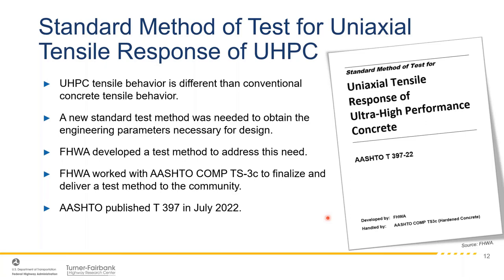AASHTO T397 was published in July 2022, so just a couple months ago. This is a test method that my group developed. We actually started working on this about a decade ago. Tested it many times. Various other labs have tested it. There's a pooled fund study that's looking at this method as well that's going to soon publish a report. But basically, it's a new standard test method that directly measures the tensile response of UHPC. And the method tells you how to both run the test and analyze the results.